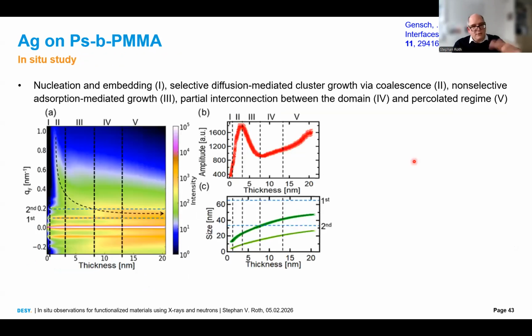Good. We can do the same. We can make the cut here. We can look at the structures, and we see again, confirming with GISAXS, an increase of the diblock copolymer signal because the silver grows on the PS. Thereby, we have an increased density difference between one domain, PS plus silver, and PMMA. Then we have a reduction again because the silver starts to grow also on top of the PMMA, and then it grows together and grows and grows, and this is the typical metallic reflectivity.